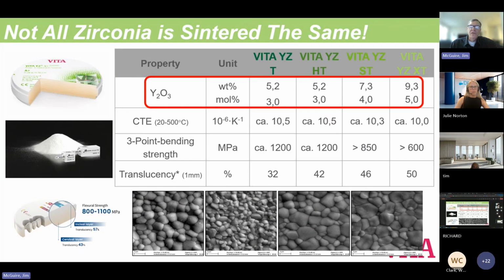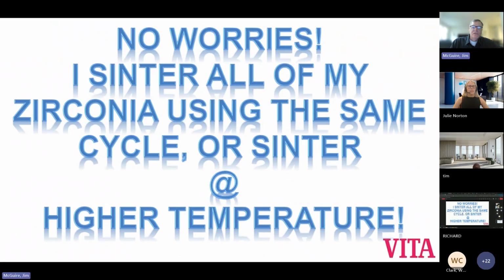So again, if you're going to do some of your own work chairside, we get a lot of calls that say, well, I've got this material from Katana, I've got this material from Ivoclar, I have this material from VITA, whoever it may be. I need to sinter it. Can I use the same sintering operation as all my other zirconia? The answer is no. Everything's made differently. Even though they're all zirconia types, they have compositions that do not sinter down to the exact same grain size from product to product. Because during the sintering process those grains shrink and collapse, and they have to fit together correctly. And they all have different shrinkage rate percentages. So at the optimal high temperature, you have to follow the manufacturer's rules of sintering.